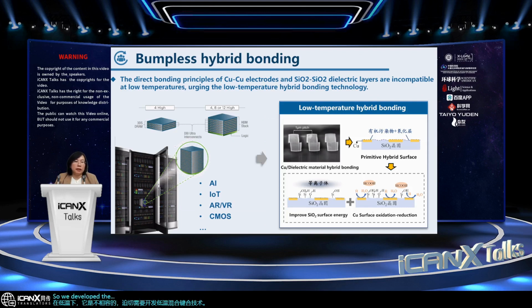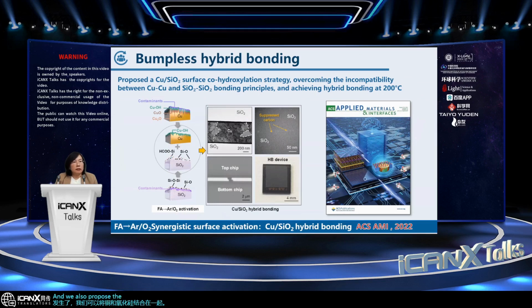So we developed a plasma activation method. We use the plasma to activate the silicon oxide wafer, and then we use the plasma to improve the surface energy, and then the copper surface oxidation occurred, and we can bond the copper and the silicon oxide together. And we also proposed a copper and silicon oxide surface hydroxylation strategy, overcoming the incompatibility between copper and silicon oxide bonding principles, and achieving hybrid bonding at a low temperature, about 200 degrees Celsius.